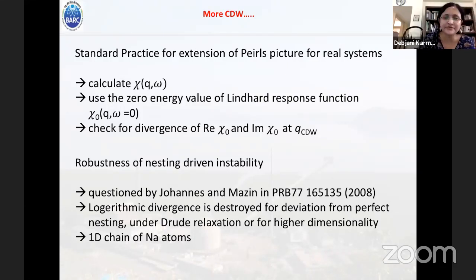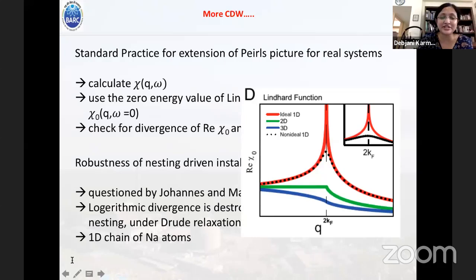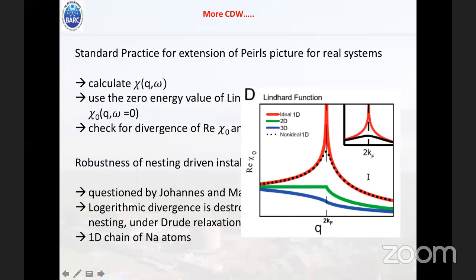Anyway, there is a one-dimensional chain of sodium atoms. What Johannes and Mazin have shown is that even after incorporation of Drude relaxation, this kind of logarithmic divergence breaks. So for a non-ideal one-dimensional system there is a very poor kind of logarithmic divergence, and even for 2D and 3D systems that does not work. So there are three types of CDW ultimately.